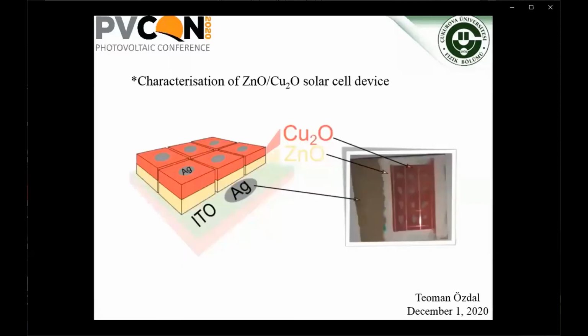Here we can see schematic and actual image of our solar cell device. Our cell was fabricated onto 2.5 centimeter square glass ITO substrate. The heterojunction was divided into squares, and then silver paste applied to create top and back ohmic contacts. Here, schematic islands, and here, the actual islands.